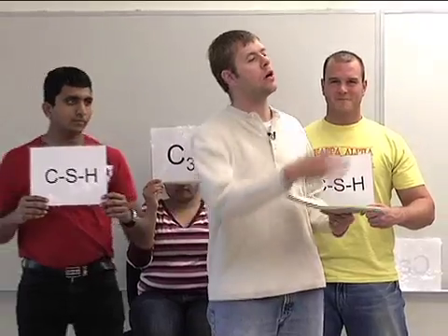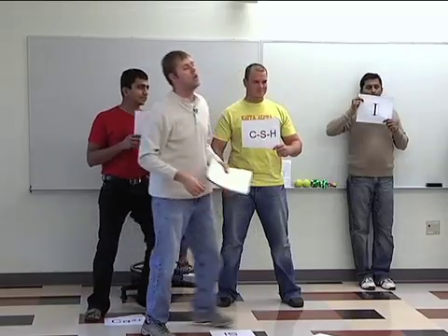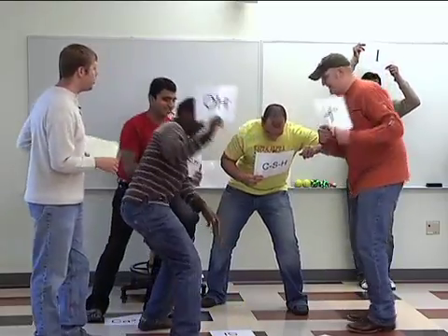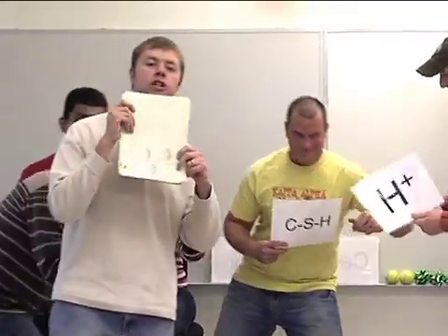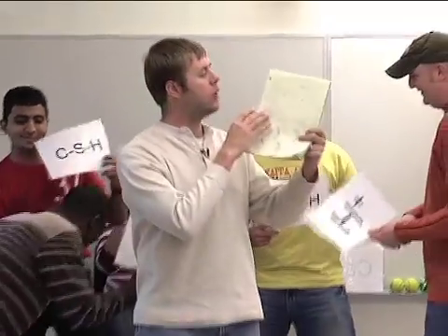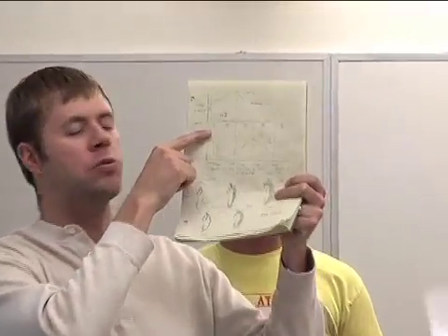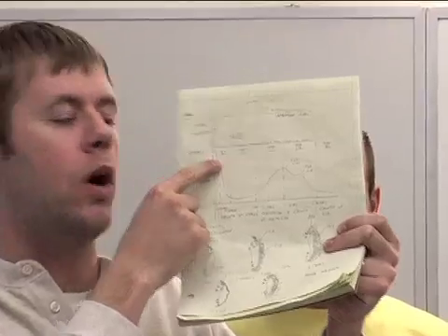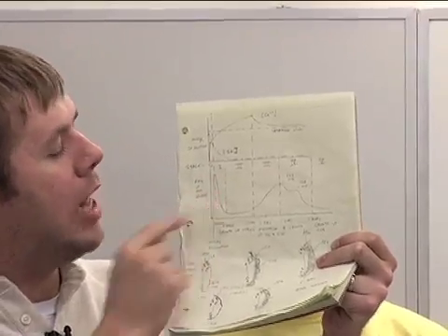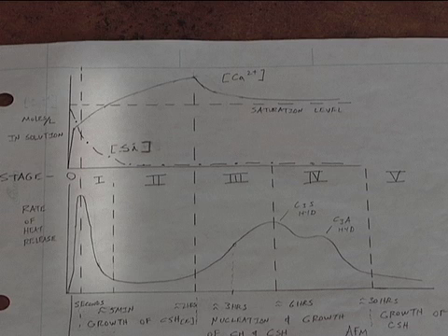So when my water molecules start to come in here, they try to get in but they don't let them. They hold them out. You'll see the reaction — the rate of heat given off actually goes from a very high level starting at the beginning of stage one and gets lower and lower and lower with time.